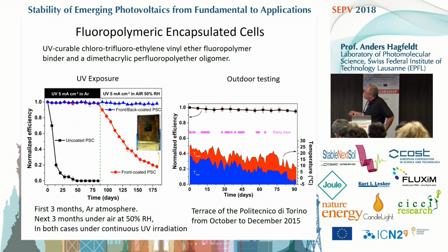If we don't have these fluorescent molecules, it degrades quickly. With the UV fluorescent molecules on top, it's stabilized. Then we add humidity, 50%. If it's not encapsulated, it degrades. But if it's encapsulated with UV light and humidity, you see a very nice stability.